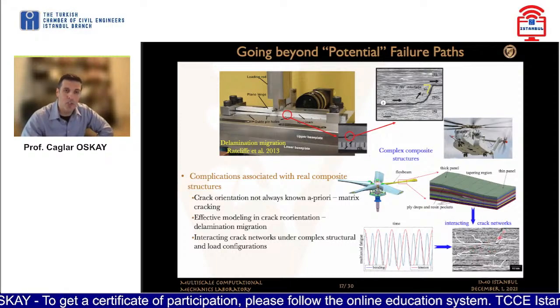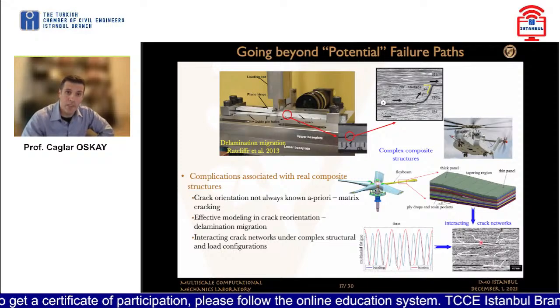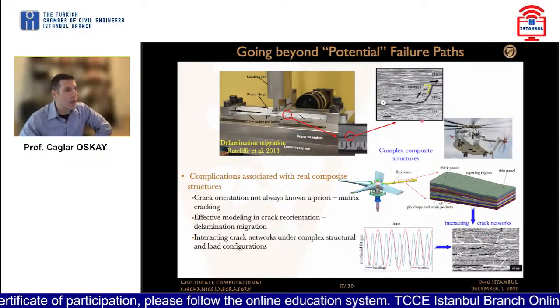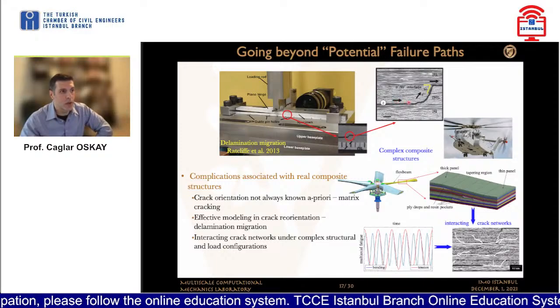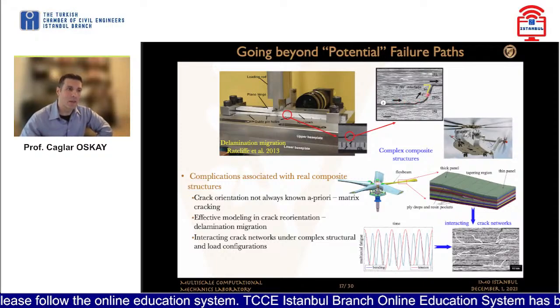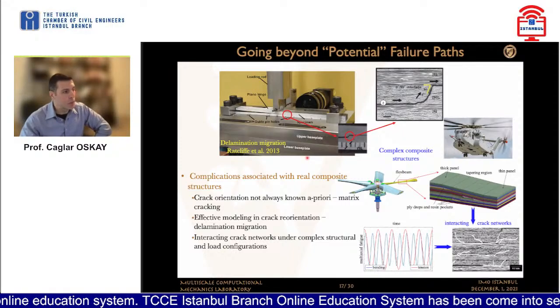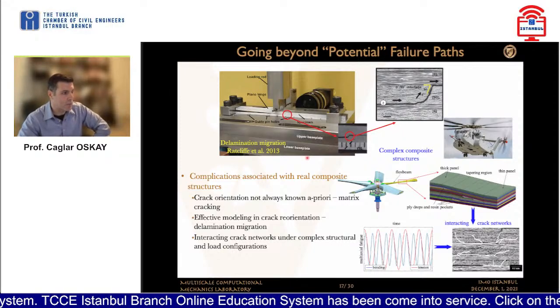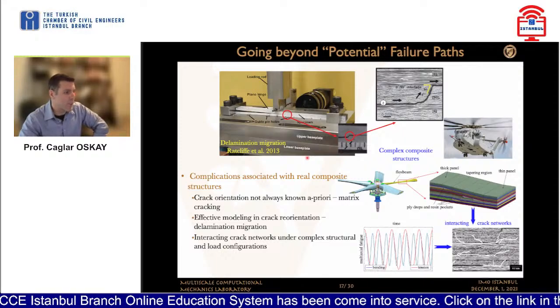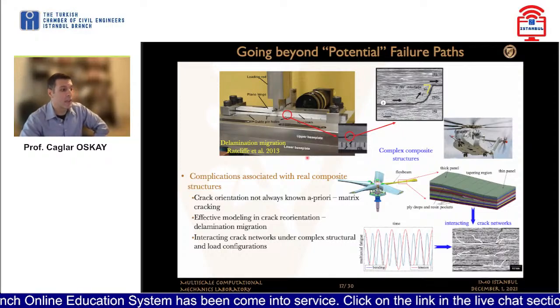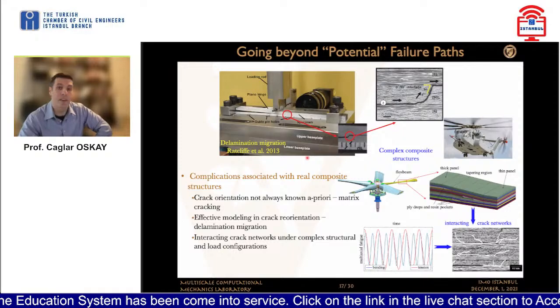As you can see, there's crack merging, crack splitting, and different cracks in different orientations that need to be taken into account. This is a delamination migration test, which we're going to analyze in a second, but it also idealizes the problem a little bit and shows a nice migration behavior that we're quite interested in as well. So the point is that the crack orientations may not always be known a priori, particularly for matrix cracking. What we would like to be able to do is model the crack reorientations in a fairly effective, computationally efficient manner. And we would also like to extend our approaches to interacting crack networks, hopefully.